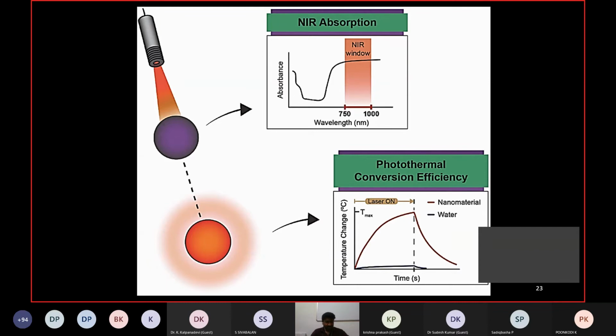Sometimes one report says they have heated up to 80 degrees, but we don't need 80 degree heating, because 43 degrees is enough. 43 to 50 degrees is enough. If you heat the material too much, that may cause further damage. So you can optimize the heating efficiency, that is one thing, and the photothermal conversion efficiency is the relationship between how much radiation is absorbed and how much heating you can achieve using the material. The photothermal conversion efficiency is what is more important, and gold has more photothermal conversion efficiency.